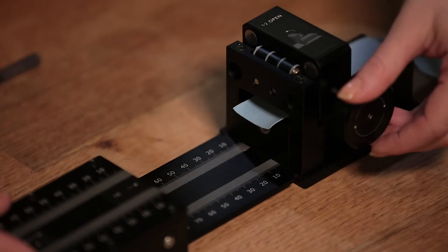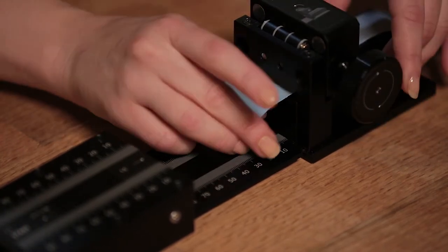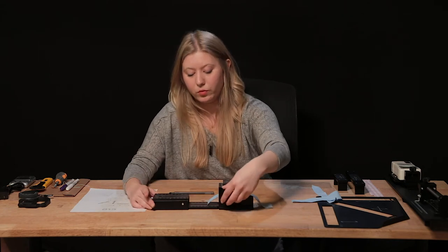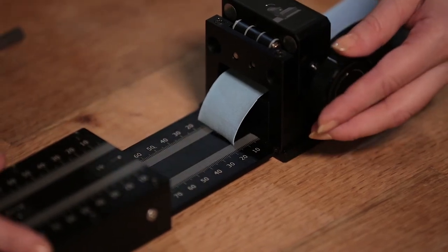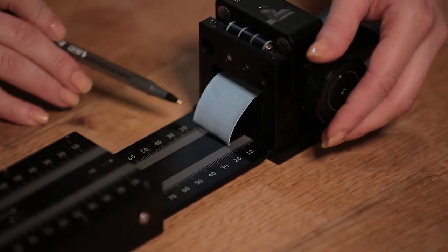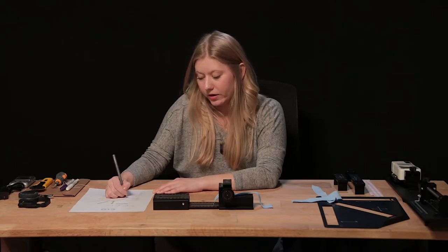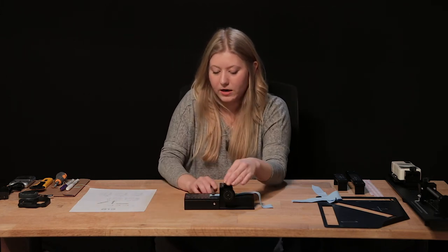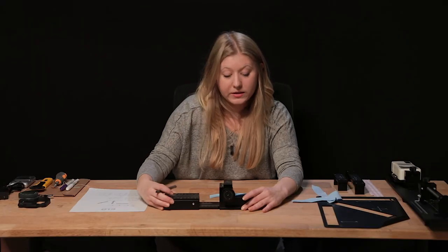Place the fabric in and start rolling forward to see where it hits the ruler. If your knit rolls under — some knits roll under a lot — push it out further than needed, roll backwards, and note the measurement at which the fabric lifts off the ruler. For mine, it lifted at 15 millimeters, so contact distance is 15. Then record the contact length, which is 29. That's it for the bend test.